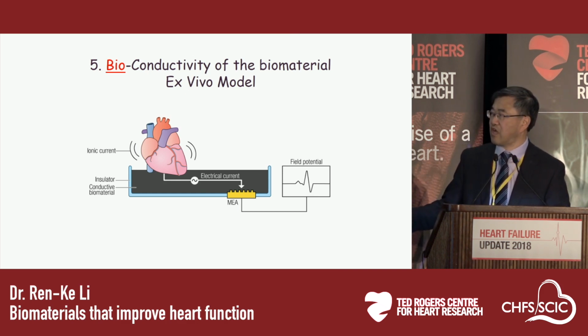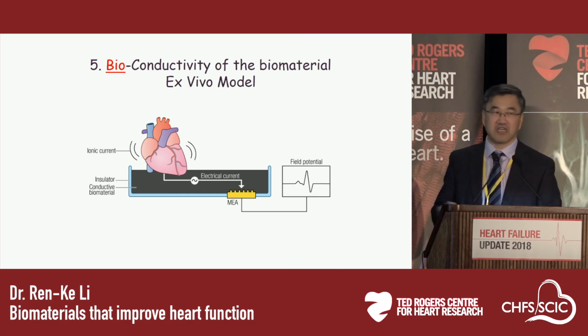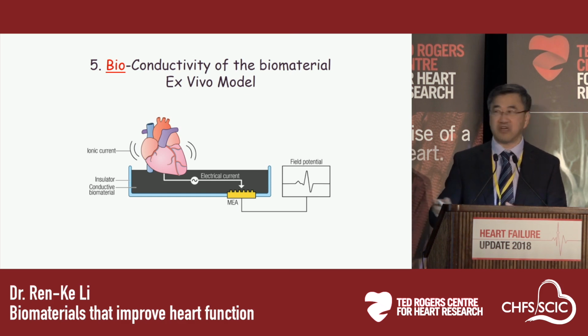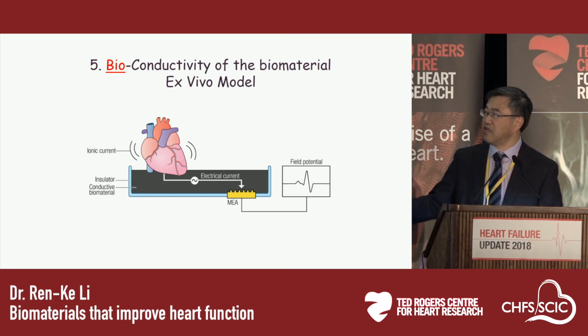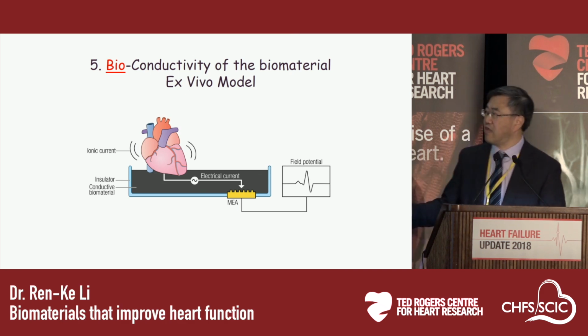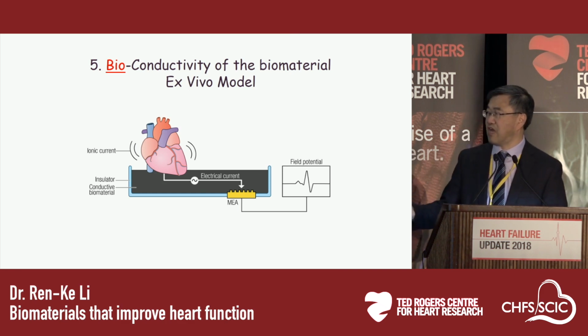At the bottom, we cut the holes. We use a multi-electrode array to measure the voltage in this conductive biomaterial. And then we take the heart, we perfuse the heart, and put the beating heart on top of the conductive biomaterial. And then we look at the voltage received by the MEA.